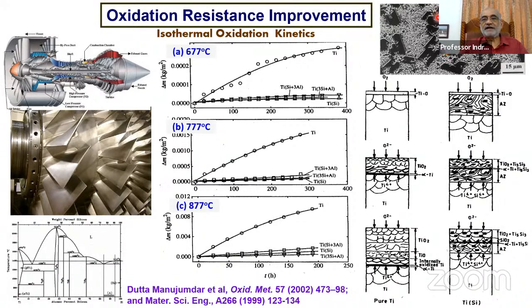oxide barrier coating, if we could have silicides, intermetallic phases, which are much more compatible to the metallic base than the oxides, if they make up 85% of the volume fraction, either as the primary phase or as a part of the eutectic, then instead of this kind of an easy oxidation process in the base metal, which is titanium in this case, when you create such a barrier layer, you prevent the counterionic transport of the oxide coming from outside and cation going inside, outside. So this oxidation is prevented. And as a result, if this is how titanium oxidizes, these silicide layers reduce the oxidation rate so significantly, even at fairly high temperature. So this is what we showed a long time back.